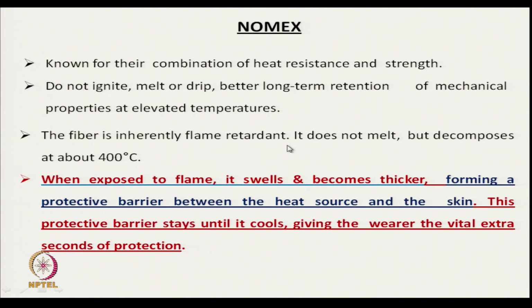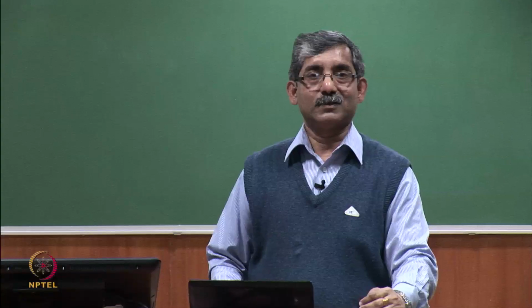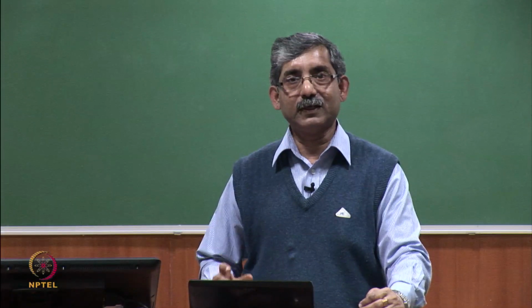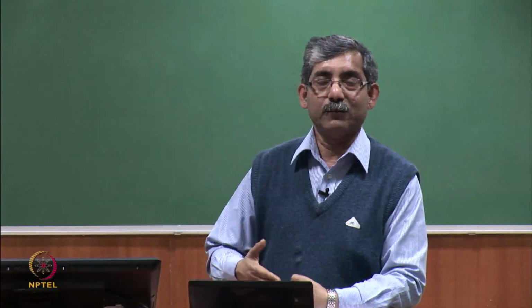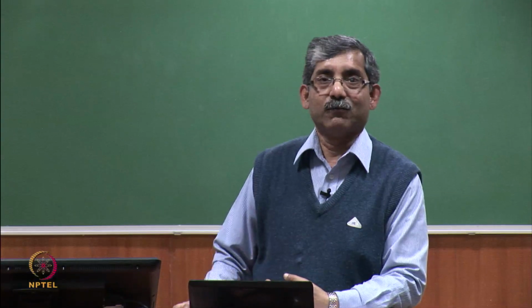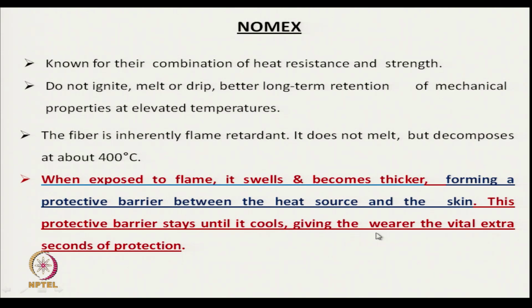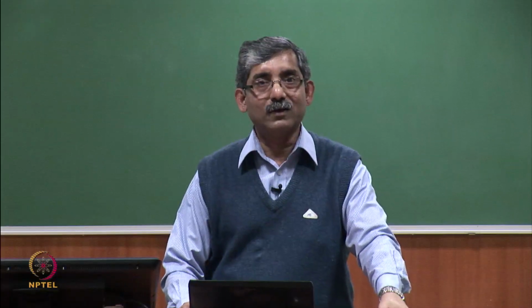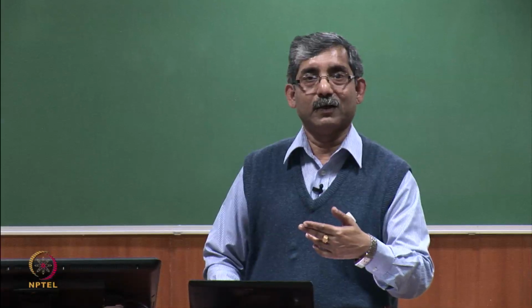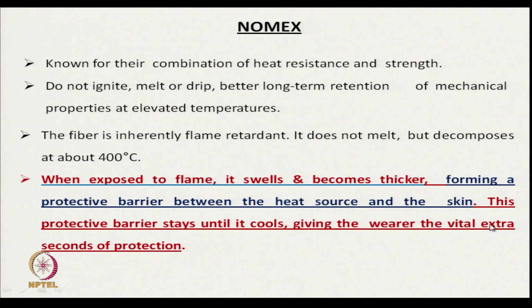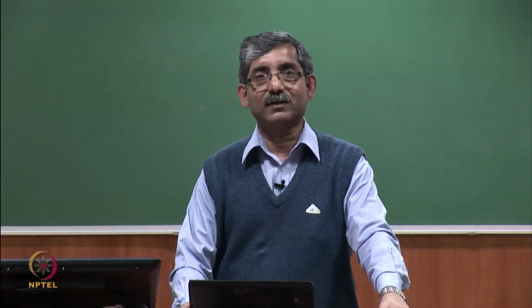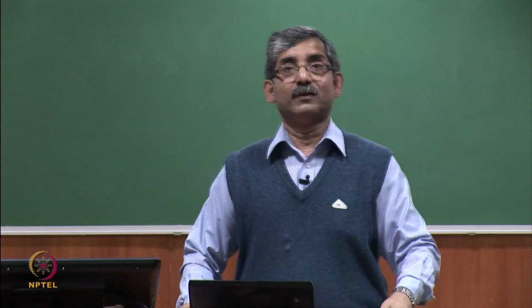Another advantage of Nomex fiber is that once this fiber is exposed to flame or high heat, it swells. That means the diameter increases, the fibers become thicker, and this makes the fabric compact. So, they form a protective barrier between the heat source and the skin due to the compact structure. Once the fabric cools down, the diameter becomes normal again, it reduces, and during this swelling they give extra protection to the wearer. This is one interesting characteristic of Nomex, which is why Nomex is used for the outer layer.